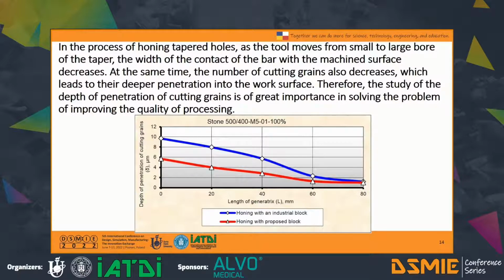Based on the data obtained, graphical dependencies of the depths of penetration of cutting grains along the length of the generatrix of the conical holes were plotted. The graph shows the depths of penetration of the cutting grains of the diamond bar into the work surface. It should be noted that when using an industrial block, the depth of grain penetration is in the range of 1.2 to 9.7 micrometers, and with the proposed block from 1 to 5.7 micrometers.